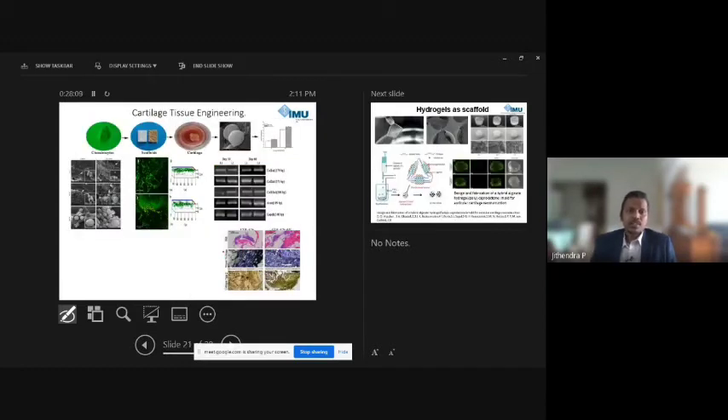In another study on cartilage tissue engineering, we cultured chondrocytes on chitosan-collagen scaffolds with and without aloe vera. The presence of the phyto compound improved cell structure growth and the morphological properties of chondrocytes — their unique spherical shape. This was confirmed by cartilage markers and histology studies showing collagen secretion, demonstrating suitability for artificial cartilage synthesis.